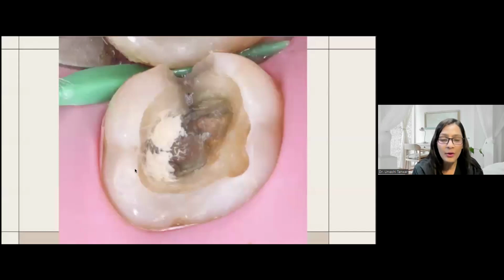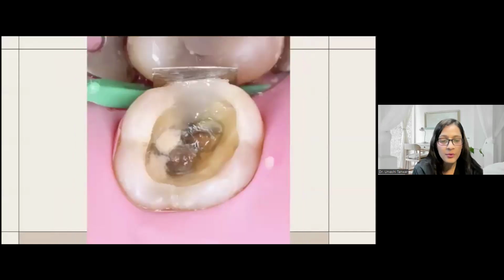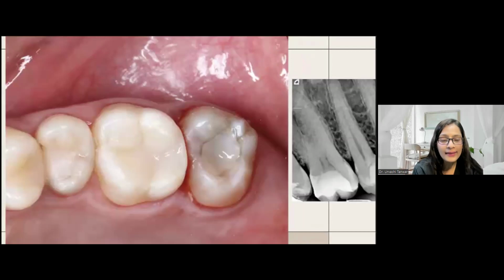So I placed Biodentine only on these two areas, dissected the crack completely in the peripheral seal zone, removed this crack as well, and then I waited for 10 minutes for the Biodentine to set completely. Okay, after which I proceeded to bond, build this layer, build the proximal wall, and then I did a composite build-up.